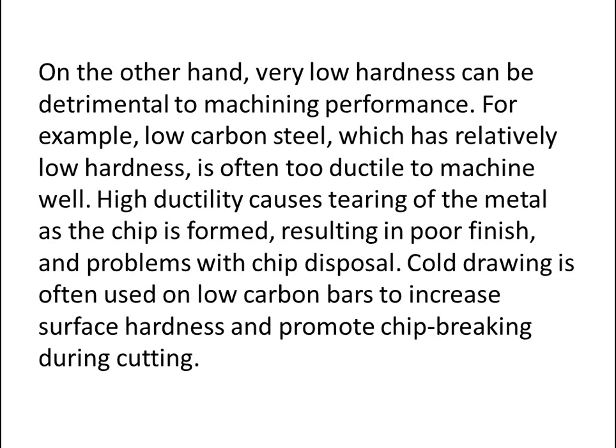On the other hand, very low hardness can be detrimental to machining performance. For example, low carbon steel, which has relatively low hardness, is often too ductile to machine well. High ductility causes tearing of the metal as the chip is formed, resulting in poor surface finish and problems with chip disposal. Cold drawing is often used on low carbon bars to increase surface hardness and promote chip breaking during cutting.